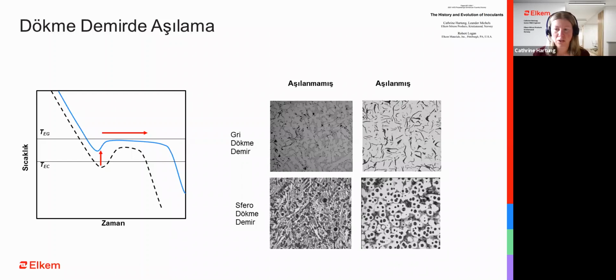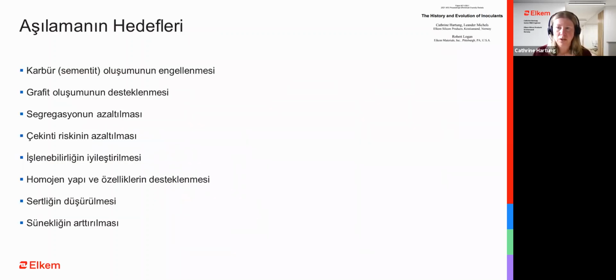And the purpose of the inoculation is then to change the structure from carbidic and undercooled to fully flake or spheroidal graphite. And this gives you the properties that you're after in the case of cast iron, compared to a hard, brittle material, which is the result if you have solidification according to the metastable system. Next. So the goals of the inoculation are to avoid the formation of carbides and promote formation of graphite. You reduce the segregation and reduce shrinkage. You have improved machinability and a more homogeneous structure and properties throughout the casting. It reduces hardness and increases ductility.